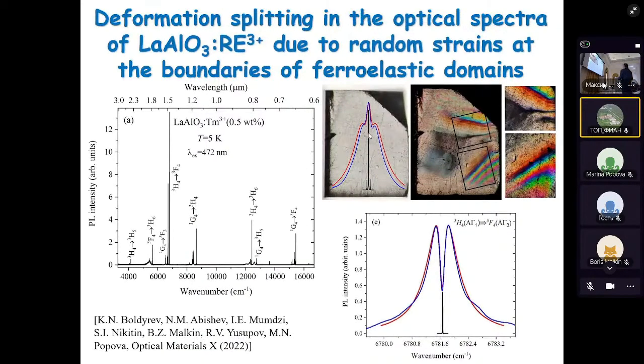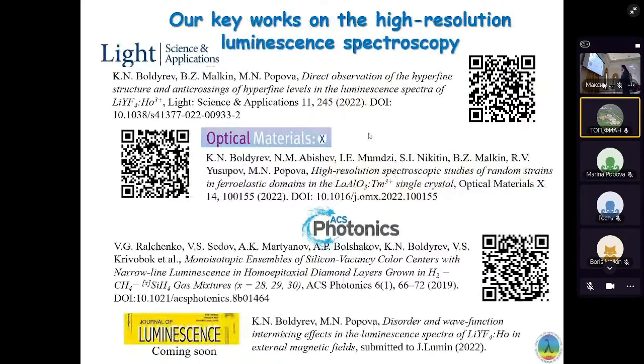Next example, we observed the deformation splitting in the optical spectra of perovskite lanthanum aluminum O3 with the rare earths holmium and thulium. We observe the deformation splitting due to the random strains at the boundaries of ferroelastic domains. This is our new publication too. So here you can see our works on high resolution luminescence spectroscopy.